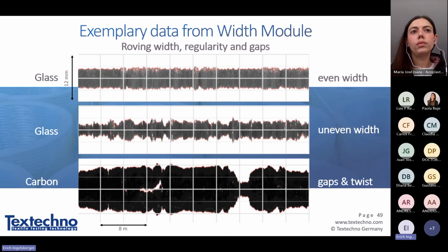Some examples of measurements: this is quite a good roving. This roving here is very uneven, meaning the spreading is not as perfect. This can have several reasons - for example a sizing effect, or what you can see here, a twist inside the roving, which prevents the fiber band, the roving, from being completely spread. You can see some gaps in between, meaning the fibers are not evenly distributed during the spreading.